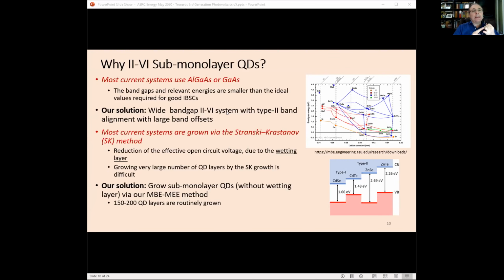two major deficiencies. One is creating a so-called wetting layer, which results in a reduction of the open circuit voltage, and it results in escape of charge carriers, which reduces the short circuit current. And the second one, it's very hard to grow very thick quantum dot layers by the Stranski-Krastanov method. So that means technically you will be reducing the possibility of light absorption.